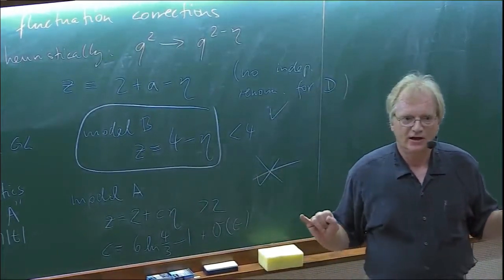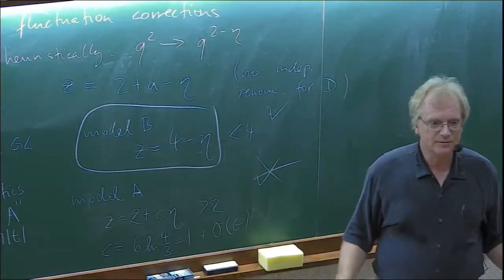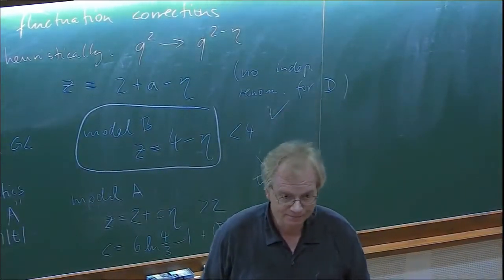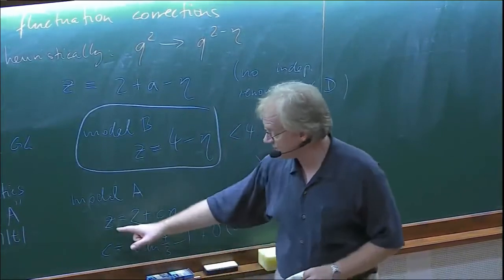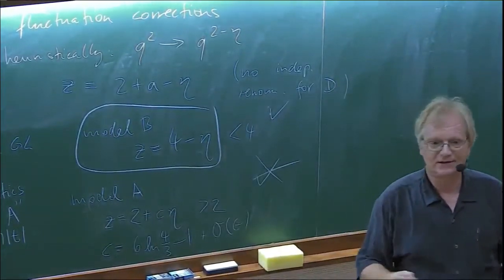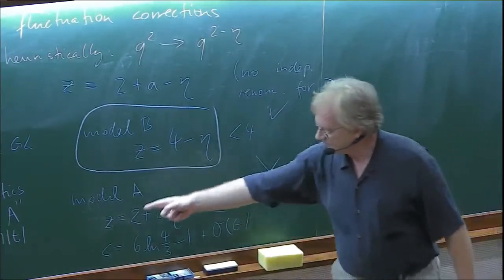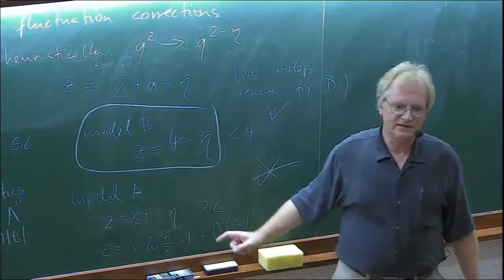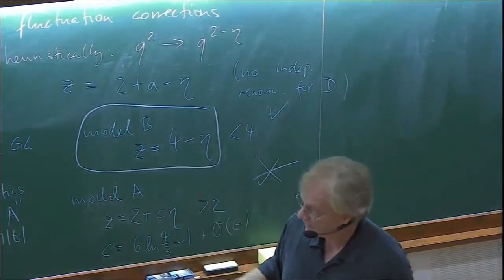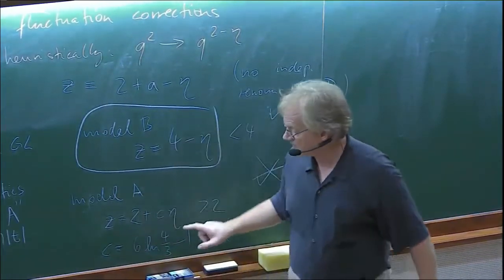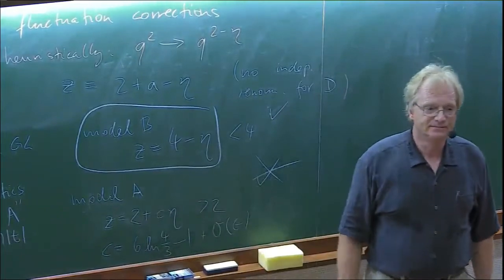Now, at the end of yesterday's lecture, I showed you experimental data for relaxation of a ferromagnetic film, where they measured z to be 2.09 in 2 dimensions. So a little larger than 2, and that is believed to be in this universality class. So it's an Ising magnet, satisfies the static exponents of the Ising model, and the dynamic exponent is this slightly larger than 2 value.